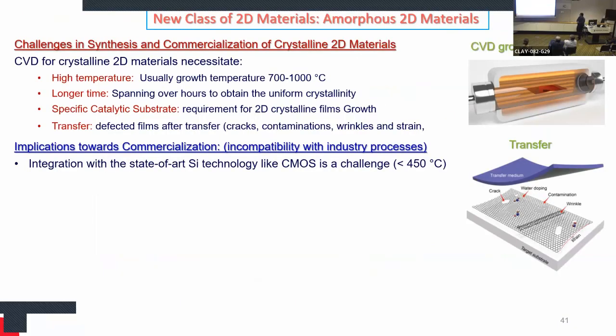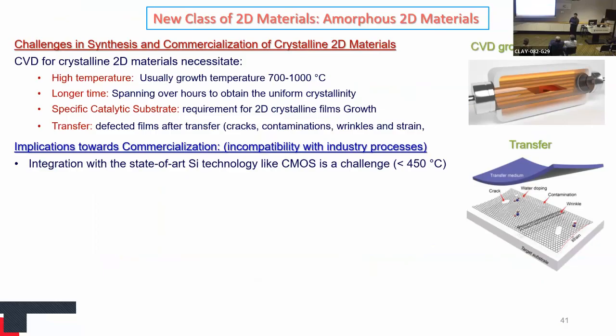So I think, yeah, I will come to the last part of my talk, which is the completely random structure, from single crystalline to defects. And now we move to the completely disordered structure, the amorphous structure. So there, of course, there are pros and cons once we want to get crystalline materials. One of the biggest issues with crystalline materials is that if you want to get high quality crystalline material, like graphene, you have to go with high temperature. Like for CVD of graphene, we have to use 1000 degrees Celsius, or a minimum of 700 or 800 degrees Celsius. Also, sometimes CVD processes are quite long and also require catalytic substrates.